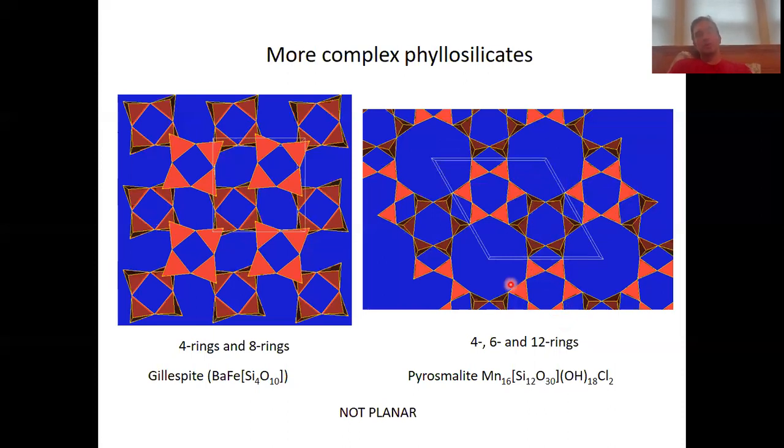Okay. So this structural motif creates additional rings. Okay, that creates these four-membered rings here, in which two tetrahedra point up and two tetrahedra point down, and it creates these very large twelve-membered rings. Okay, with alternating pairs of tetrahedra, in which pairs either point up or point down.